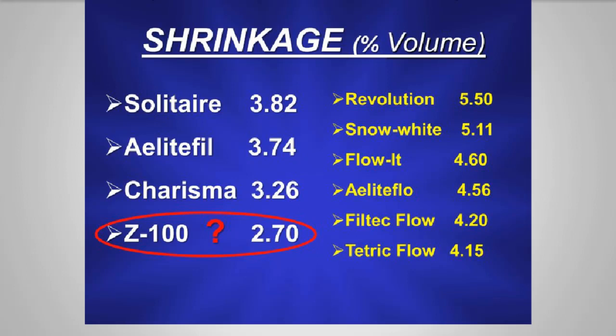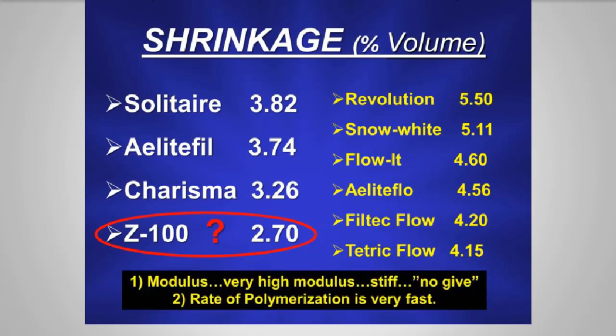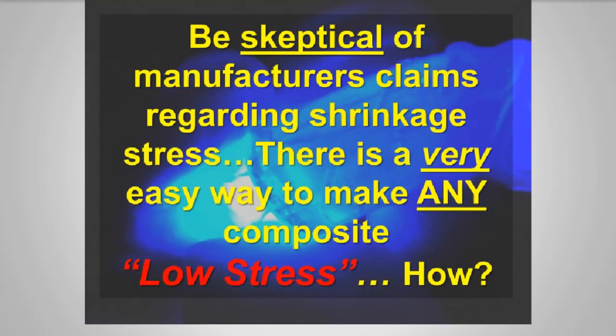Now, how can the composite that shrinks the least induce the most stress? Well, in the case of something like Z100, it probably mostly has to do with modulus, which is a measurement of the relative stiffness of a material. A high modulus material is not very bendable or pliable, while a low modulus material is. The Z100 is a very high modulus, it's very stiff, very little give to it, and that fact alone causes it to induce more stress at the adhesive interface when it cures. So be very skeptical of manufacturers' claims regarding shrinkage stress in composite materials.